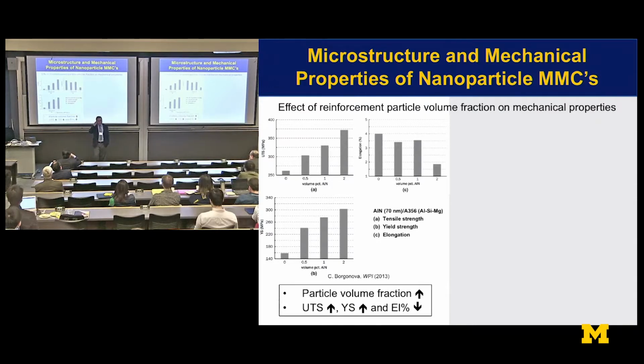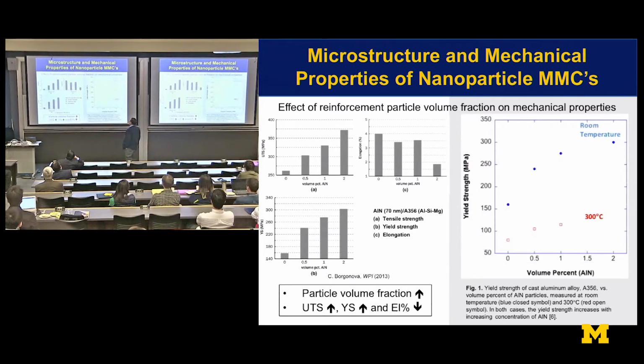People had been doing that by putting in 10, 20 micron particles to refine grain size, and so to have a dispersoid strengthened casting. The key is, even though I'll argue metallurgy has been dealing with nanomaterials forever, we just didn't call it that because that's what nature provides. Working with our colleagues at Worcester Poly in Massachusetts, we found if you can put in nanometer scale particles, and John, we actually call these ceramic particles, even though they're not oxides, you can get dramatic improvements in strength. And more importantly, we can retain the properties to higher temperatures. And that's really the goal.